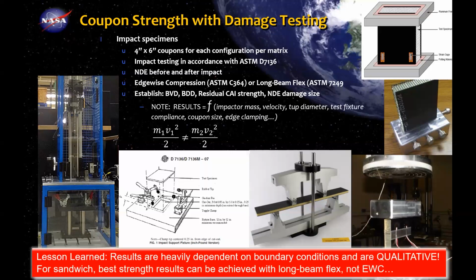I want to make a quick point that you'll find people have been using drop towers that are really aircraft energies, which is 50, 60, 100 foot-pounds, and they use a fairly high mass. If you get into a study about impact damage and you're trying to actually characterize or size or interrogate the kind of threat that is real to you, for most of our spacecraft world threats, they're tool drops or somebody's elbow banging into a structure, right? On something in the wrong place.